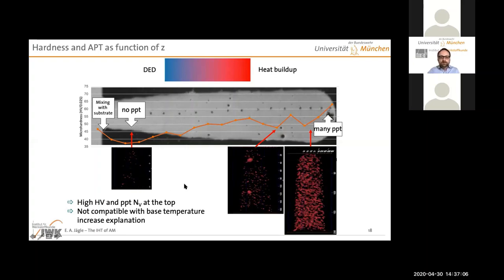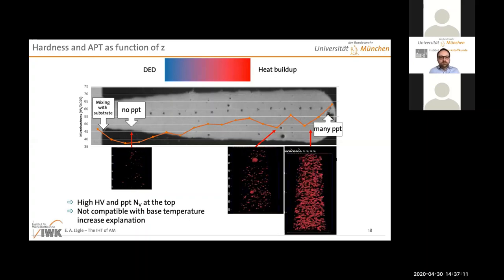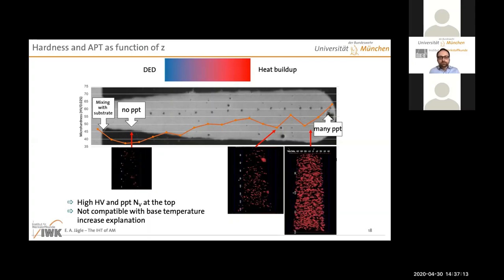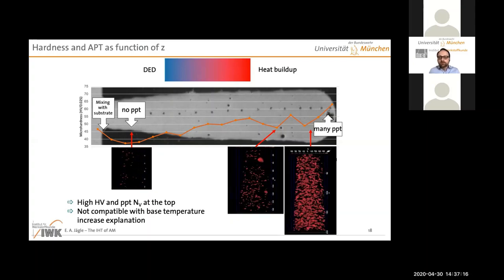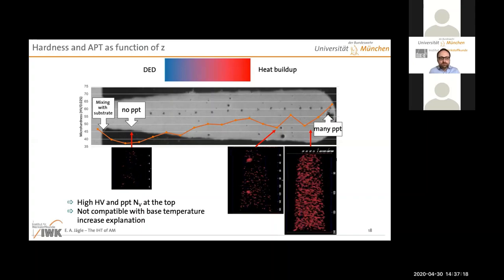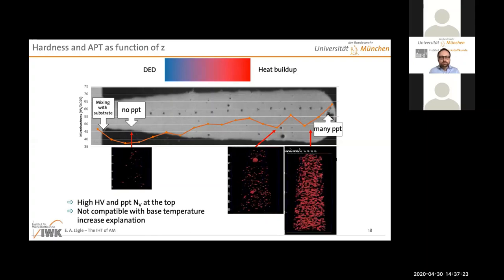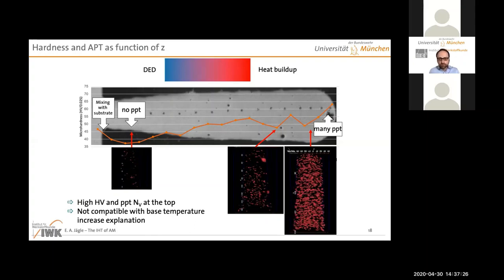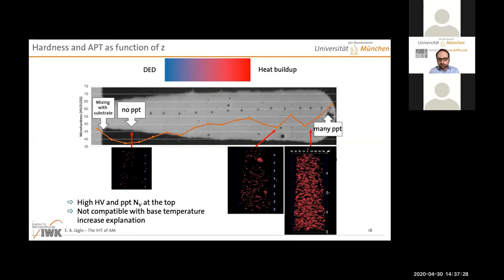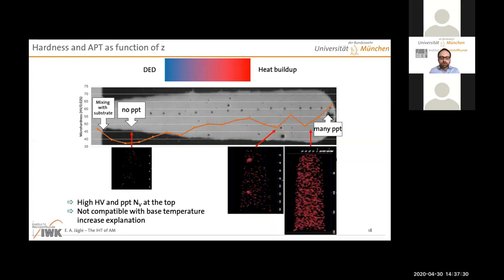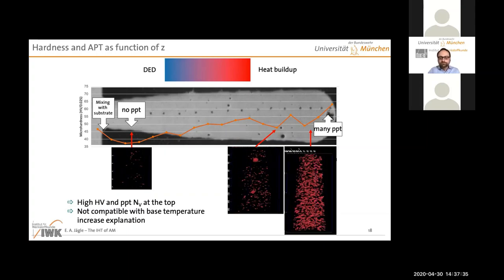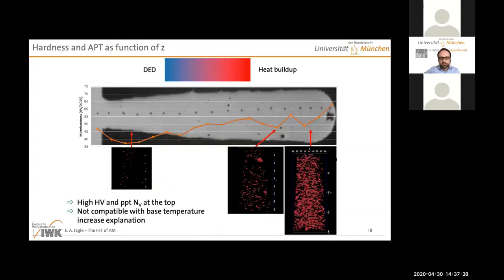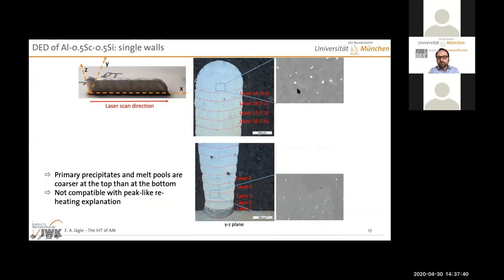Okay, so again, this is incompatible with a peak-like reheating, and it is also incompatible with an increase in base temperature, because with an increase in base temperature you would keep the bottom part of the sample way longer at these relatively elevated temperatures than the top, and therefore we would expect a higher hardness at the bottom, but we're seeing a very high hardness at the top. So what's more or less left as an explanation is the cooling rate. And the cooling rate makes a lot of sense, because a lower cooling rate also means that you have more and coarser primary precipitates.